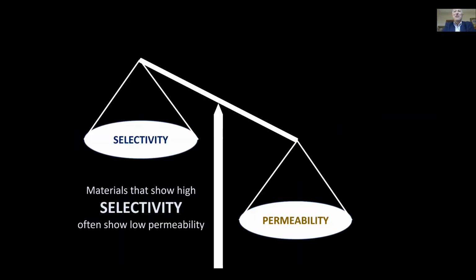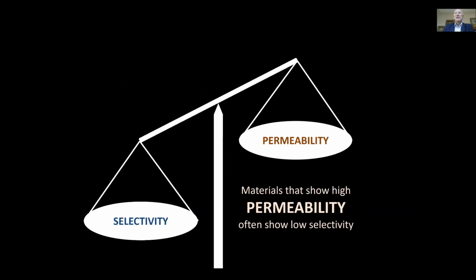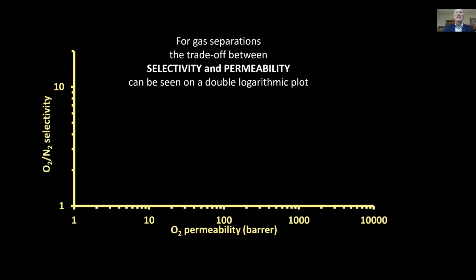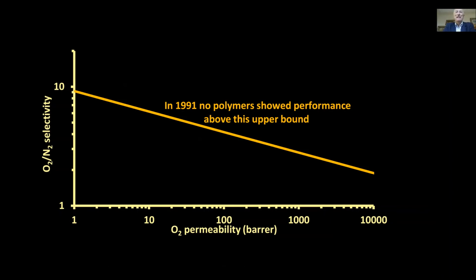Now, the problem that we face as researchers is that we can design materials that are very selective, but often materials that show high selectivity have low permeability. We can design other materials to be very permeable, but materials that show high permeability have low selectivity. There's a trade-off between selectivity and permeability. And we can show this on a graph, a double logarithmic plot of selectivity against permeability. In fact, in 1991, a guy named Lloyd Robeson took all of the gas separation data for polymers that had ever been published and plotted them all on a graph like this. And he drew a line, it's that line there, the 1991 upper bound, and in 1991, there were no polymers which performed better than that line.